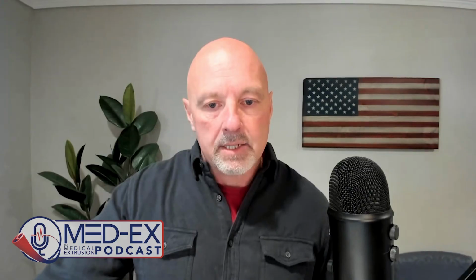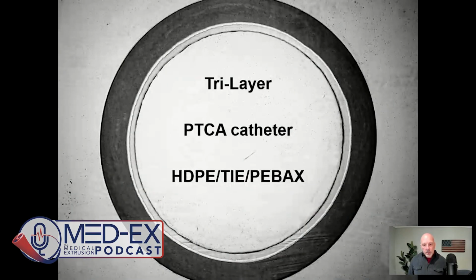Very similar chemistries. An example of the co-extrusion of dissimilar materials is a PTCA catheter. Now, this is a common tri-layer structure used in med tech with a high-density polyethylene inner layer for lubricity and a Pebax or sometimes nylon 12 outer layer. And because these two materials are dissimilar, it requires an adhesive layer, very thin, maybe 1/1000th of an inch wall thickness layer of Plexar, for instance. So this is an example of dissimilar materials.